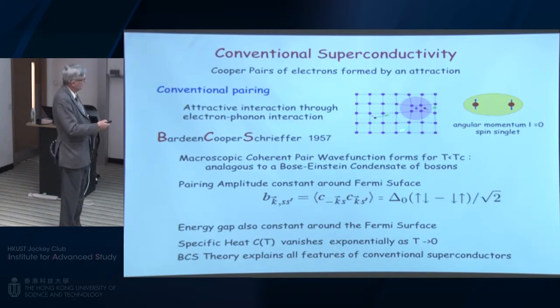And a cartoon to illustrate this effect is that if one electron goes through, it polarizes the lattice, and a second electron follows and sees this polarization, so one generates an attractive interaction. And this attractive interaction, below a certain temperature, can lead to a macroscopic pair wave function analogous to the Bose-Einstein condensation of bosons. The pairing amplitude in their model is essentially constant around the Fermi surface. This pairing amplitude causes an energy gap, and the specific heat, for example, vanishes exponentially. And the BCS theory essentially explains all the features of conventional superconductors.